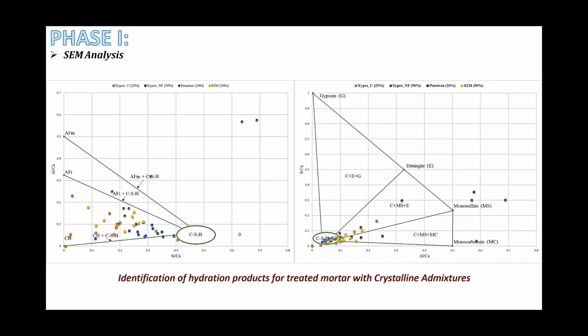Also, to identify if there is gypsum, ettringite, or monocarbonate inside, I plotted the sulfur to calcium atomic ratio over the aluminum to calcium. And as mentioned earlier, one of the products, out of the four, Penetron, is somehow scattering around the ettringite and also monosulfate, which shows that these crystals or these products may not help in enhancing the self-healing and may be harmful for the concrete.